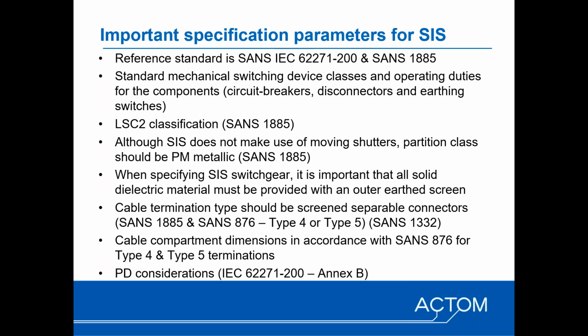And then lastly, some thoughts. Johan has shown us videos and described in detail the partial discharge phenomena. So by virtue of the earth screen layer, the concern over surface discharge, in other words, the dry band arcing associated with leakage currents along the surface of an insulator, is eliminated, as well as corona, because there's no exposed insulation. There is the possibility of voids within the solid dielectric, and that comes down then to the quality of the manufacturing and the routine testing of the switchgear.